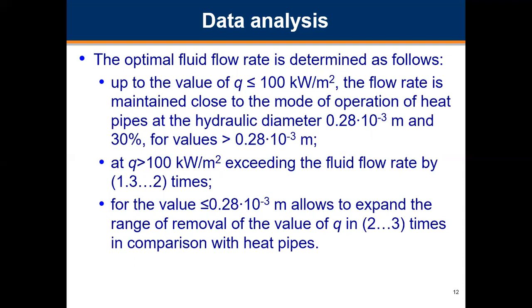Therefore, it is advisable to introduce the concept of optimum liquid excess, which establishes a uniform temperature viewed along the height and length of the heat exchange surface. The optimal fluid flow rate is determined as follows. Up to the value of Q less than or equal to 100 kilowatt per square meter, the flow rate is maintained close to the mode of operation of heat pipes at the hydraulic diameter 0.28 times 10 to the power of negative 3 meters and 30% for values greater than 0.28 times 10 to the power of negative 3 meters at